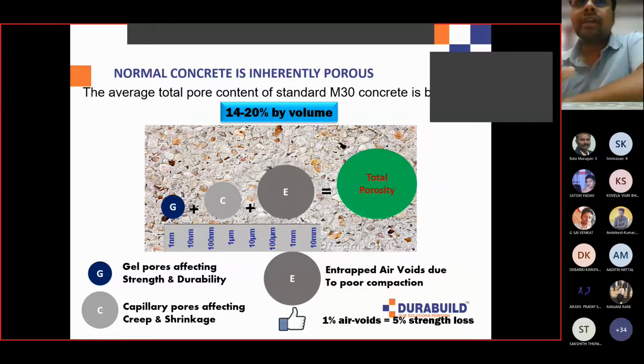Normal concrete is inherently porous. It is very well known. The average total pore content of any M30 grade of concrete will be anything between 14 to 20% by volume. Many of you have already read about it. It's a bit of a revision that there are mainly three major pores that you will find inside a concrete. There are the gel pores, which affect the strength and durability. There are the capillary pores, which affect the creep and shrinkage. And then you have entrapped air voids, which are due to poor compaction. And I think you also know there is a rule of thumb that for every 1% of air voids, there is a 5% strength loss.